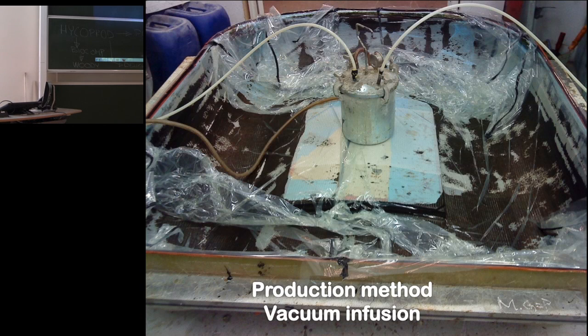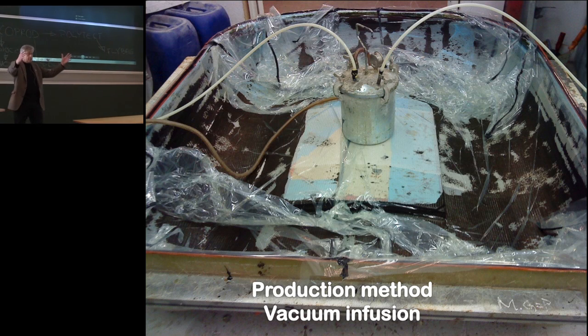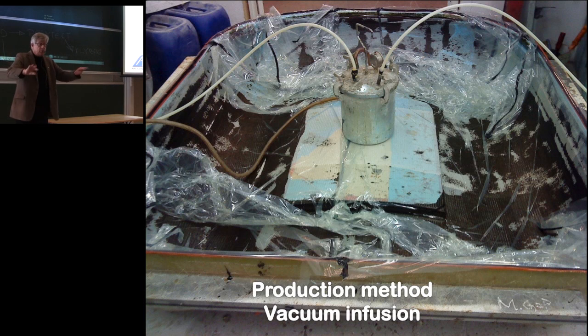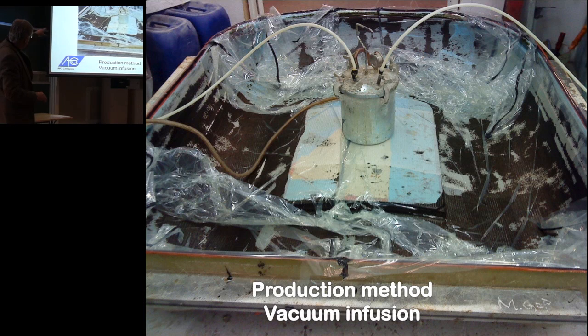And we used a vacuum technique. We took this negative mold, put the fibers inside, put the balsa wood, put more fibers. We put on a vacuum bag, an extremely flexible foil. Then we tightened it all around and had an outlet around with spiral hose, and an inlet in the center, and then we put on a vacuum pump. The flexible bag went down very hard and pressed between every single fiber, really tight. And when that was stabilized, we had done a lot of tests on the laminate, as I told you,